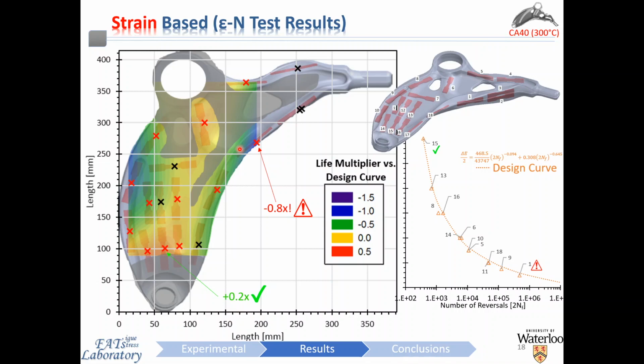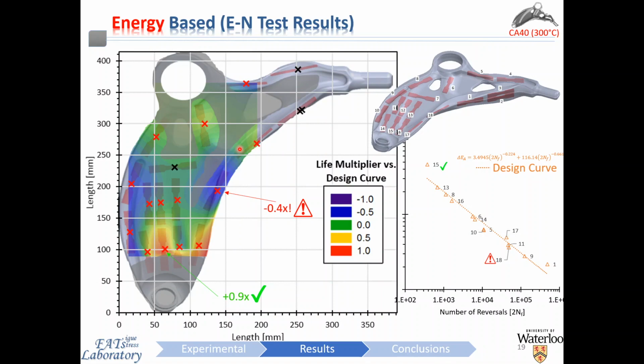This provides confidence in the fact that both comparison methods that we've investigated so far indicate similar trends in the behavior. Finally, when comparing on an energy basis, the story is similar to the previous slide, where the contour level is even further exaggerated to highlight these differences in the spatial variation throughout the control arm. Any differences observed here are more closely linked to defects within the material, as the spatially varying thermomechanical history would manifest itself as a different level of cyclic strain energy density. So we can see a much closer representation of the design curve to all of the data points, being very much not scattered or scattered very closely around it.